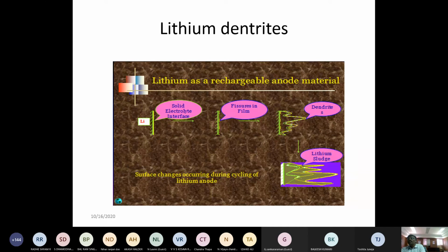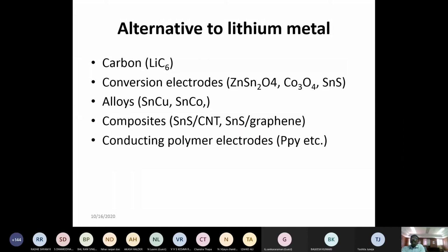So the dendrite will be formed in the form of needle-like structure, and it will puncture the membrane and it will get short circuited. So we are still not able to use lithium metal as anode, and we are not able to commercialize. And there are some alternatives to lithium metal. For example, you can use carbon.